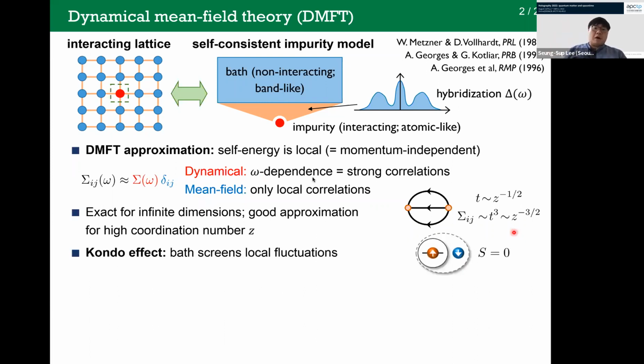And being mapped onto an impurity model, now it becomes a matter of the Kondo effect. So the impurity or a single lattice site can have charge, spin, or orbital fluctuations, the quantum fluctuations. And these fluctuations are screened by surrounding electrons in the lattice or the electrons from the bath. So they form a screening cloud, and outside of the cloud, the rest of the system cannot see these local fluctuations. So basically, via DMFT, we can treat the problems in the lattice systems in terms of the Kondo effect.